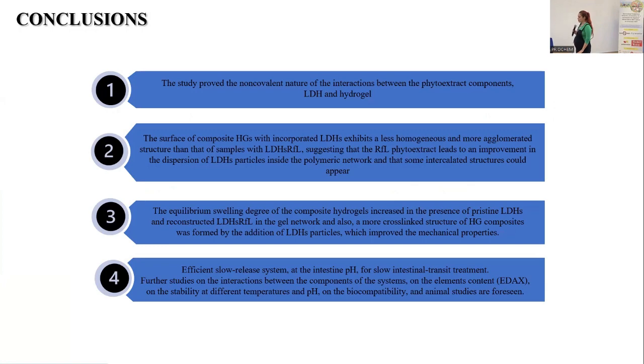The equilibrium swelling degrees of the composite hydrogel increase in the presence of the LDH and the LDH with the phytoextract in the gel network, and the study also presents an efficient slow release at intestinal pH for slow intestinal transit treatment. For further studies, there are foreseen studies on the interaction between the components of the system, on the element content, and on the stability at different temperature and pH, biocompatibility, and animal studies. Thank you for your attention.